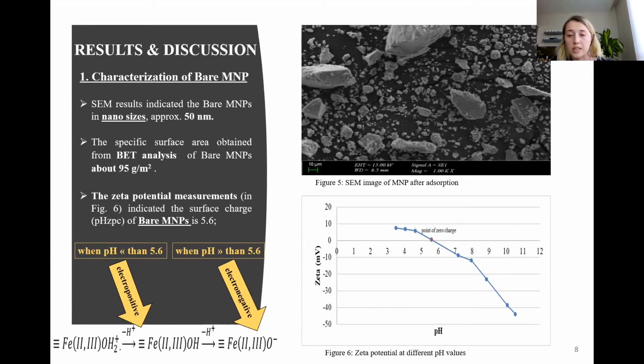And the zeta potential measurements indicated that the point of zero charge of bare magnetic nanoparticles was 5.6. And it is clearly understood that the magnetic nanoparticle surface charge is electropositive when the pH values are lower than 5.6, and it is electronegative at pH values higher than 5.6, and a pH value less than 5.6 would be preferred for negatively charged phosphate ion adsorption.